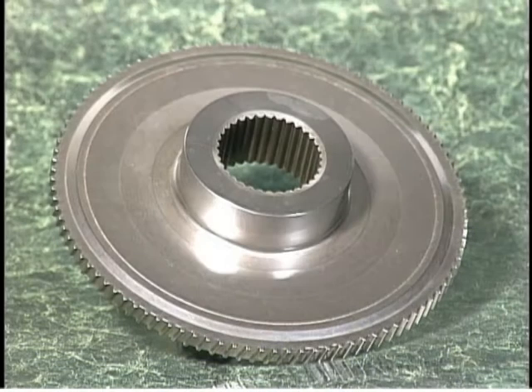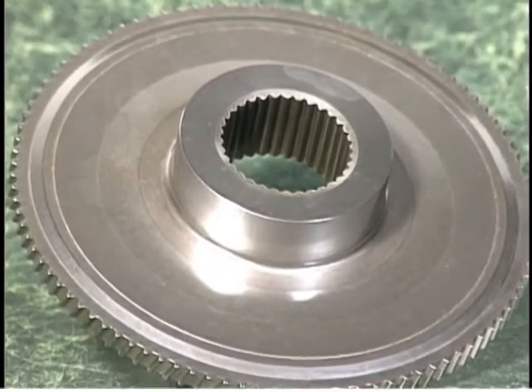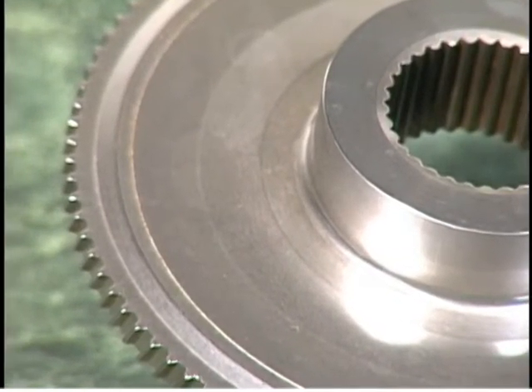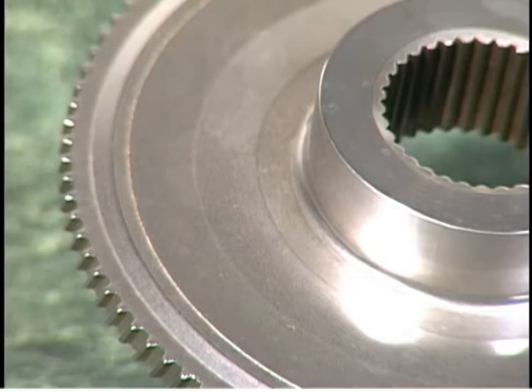The hub, which operates in a Ford torque shift truck transmission, was made using warm compaction to a minimum density of 7.2 grams per cubic centimeter and a minimum ultimate tensile strength of 155,000 psi. It is formed on a 1,650-ton compacting press utilizing 5 molding levels.